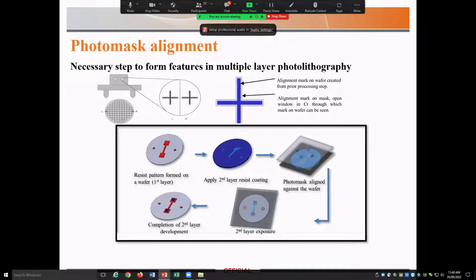As I mentioned, in a microfabrication process, we may have a few steps of lithography. So when we are dealing with this multi-layer photolithography, photomask alignment is a very, very critical step. Basically, we may have several masks. Some can be used to generate patterns for etching processes, and the other ones can be used in lift-off processes to make metal electrodes. So the main point is that each layer has to be precisely and within specification aligned to the previous layer and subsequent layers. Even minor misalignments can ruin all the devices on your wafer.